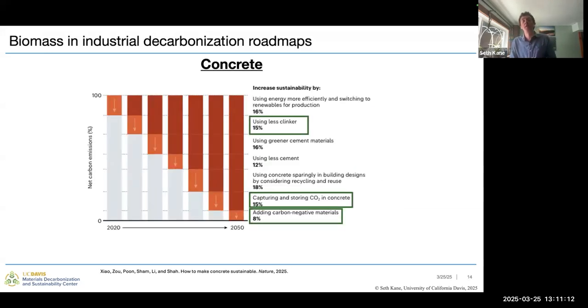And so when we look at roadmaps for decarbonizing concrete, this figure is from a paper that was published in Nature about a month ago. There's a number of different ways we can integrate biomass to do this. So here I've highlighted using less clinker. If we're replacing primary clinker with biomass-based products, we're using less clinker. Potentially integrating these materials can increase the porosity of concrete, which might allow for more CO2 capture and storage. And then if we're adding biochar, as we saw in the previous slide, we're potentially creating carbon negative materials that are being added in there. And so these can play a role there.